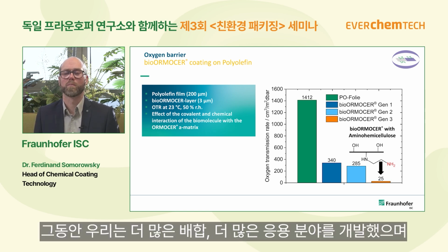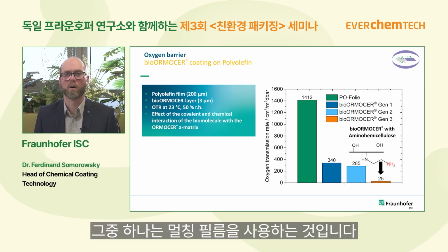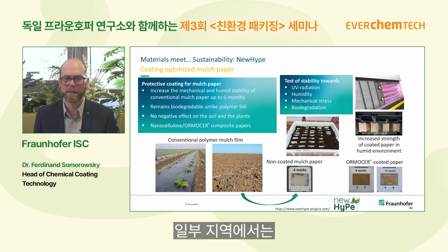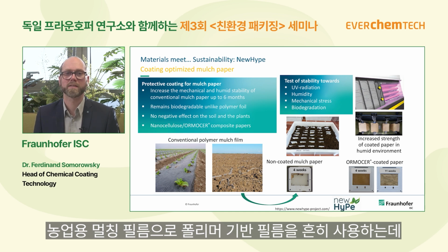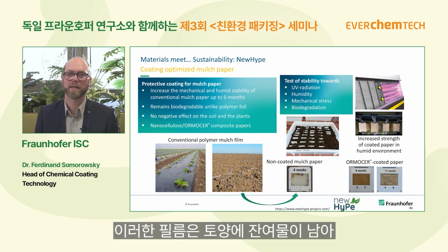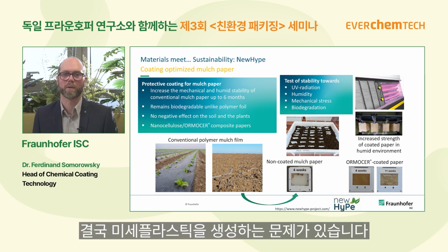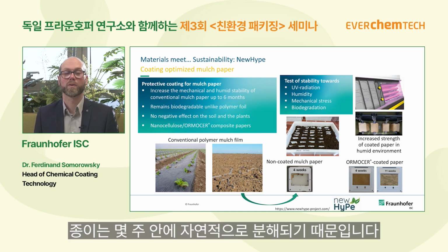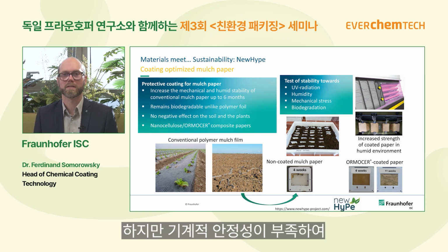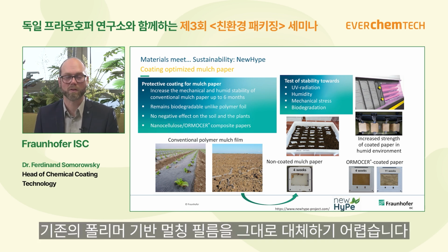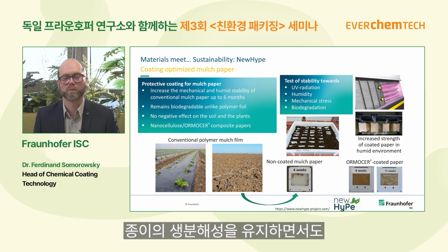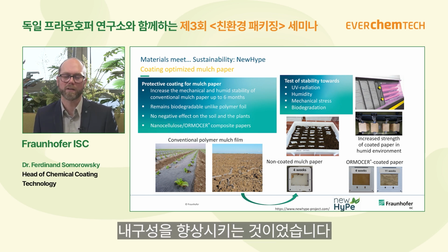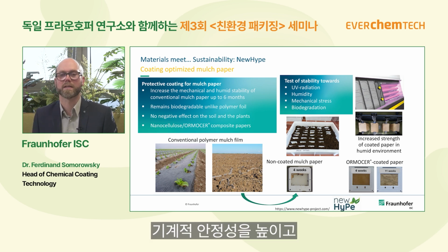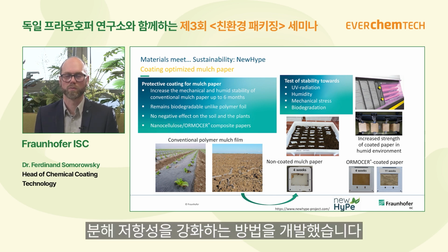In the meantime, we developed further formulations, further applications, and one is the use of mulch films. So in some areas, it's very common to use such polymer-based mulch films, and the problem here is that they stay very dirty on the film, on the fields, on the soil, and they will be mulched, and it generates microplastic. An ideal alternative is paper, because it degrades after a few weeks. But the problem is that the mulch paper is not mechanically stable, so you cannot use it as normal mulch polymer films. And the idea of this project and what we achieved is that we coat this mulch paper with a bio-Ormocer, and it helps to stabilize and improve the mechanical stability, but also improve the resistance towards biodegradation.